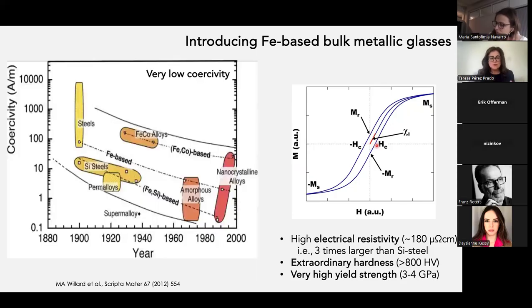Let us then review the coercive fields, the coercivities, of different families of alloys. Here in this domain we have the silicon steels, and here, in this orange domain, we have iron-based metallic glasses. As you see, there is a wide dispersion because, of course, we have many different types of alloys within iron-based metallic glasses. But there is high potential for some compositions to have a very, very low coercive field, and thus to reduce these magnetic losses. But not only that. If we are able to stabilize these materials in a fully amorphous form, they have high electrical resistivity, three times larger than silicon steel, and they have extraordinary hardness. Structural function is not the main function here, but of course we always want robust components, so they have high hardness.